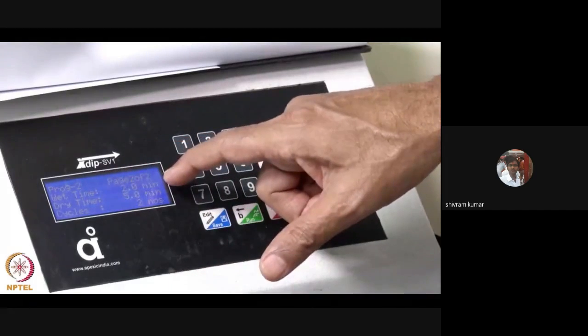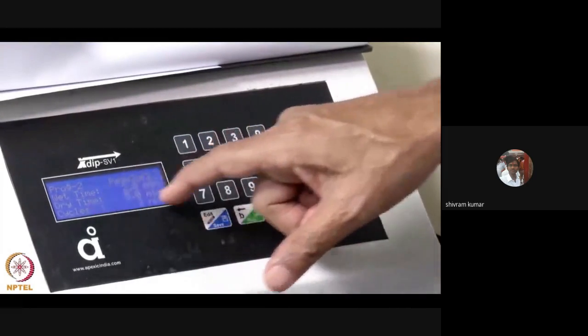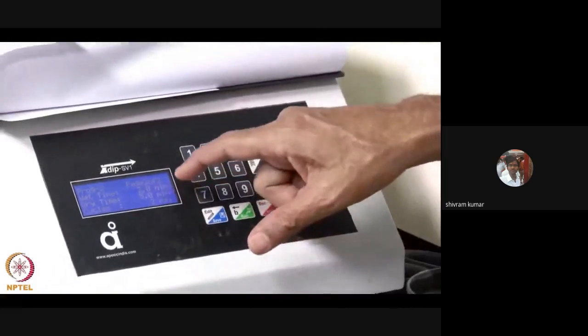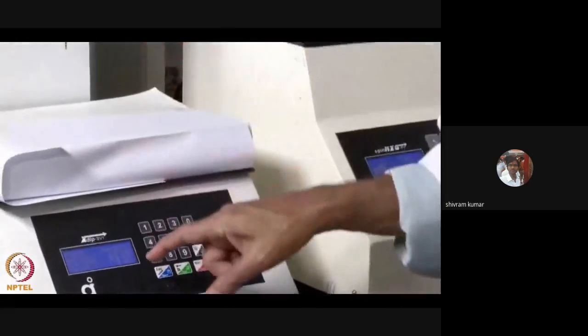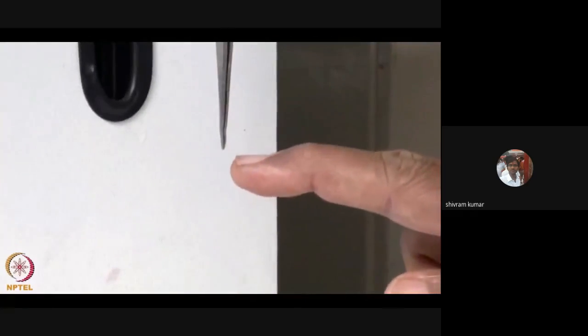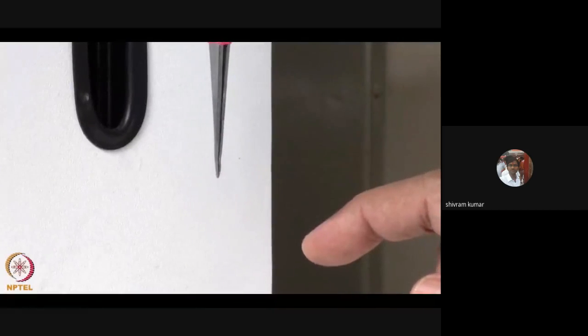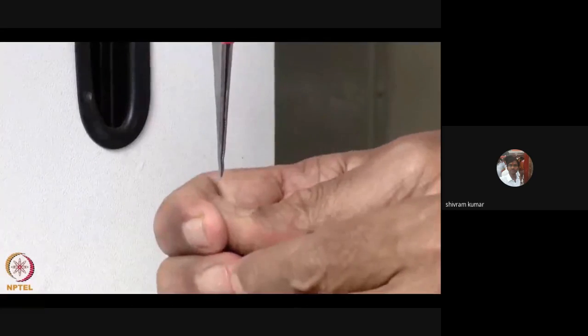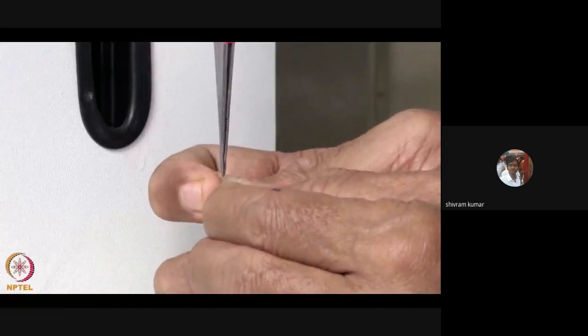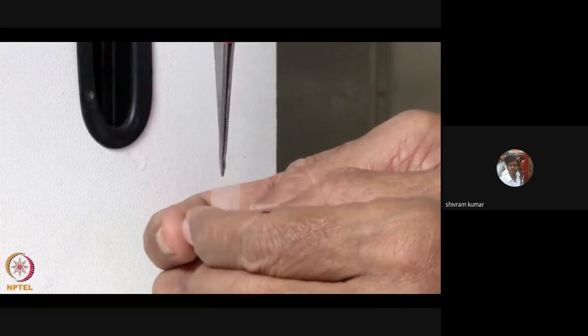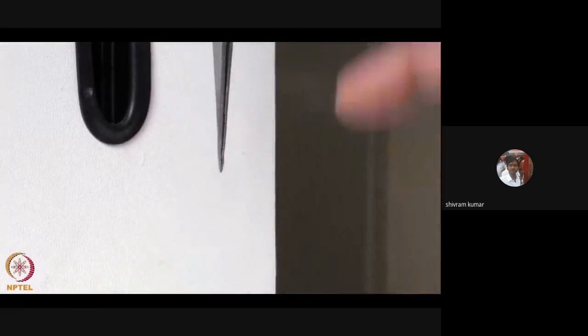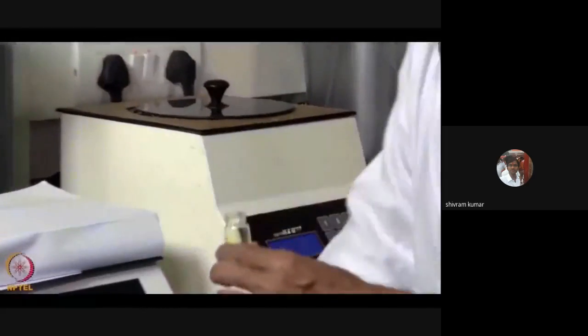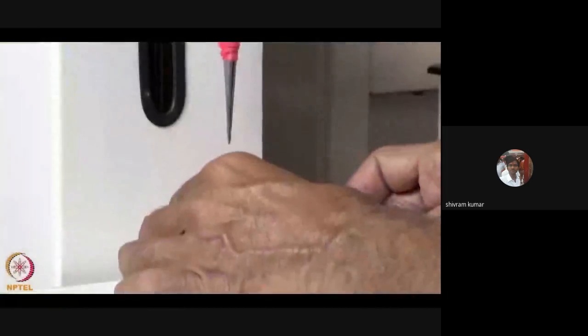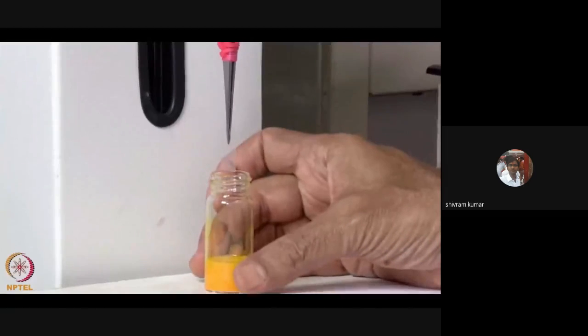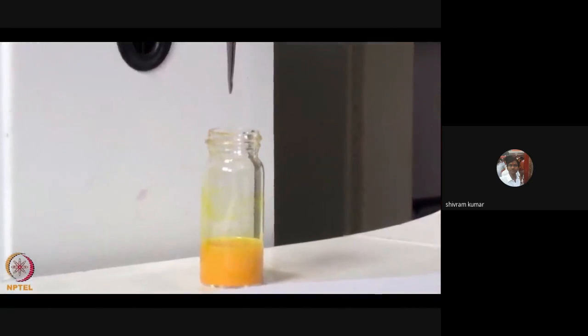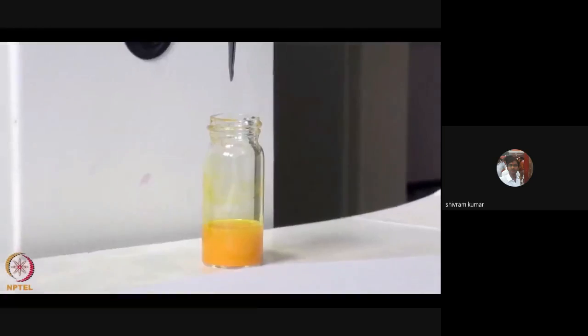It gives you how long the drying has to take place in minutes, and then how many times you want to repeat. So here I have given 2 cycles, so we can do it 3 cycles, 4 cycles, many cycles. You need to place the film at the tip. This is the polyester film. So you place the film here. Curcumin solution. The curcumin solution is placed below, and we start the run.